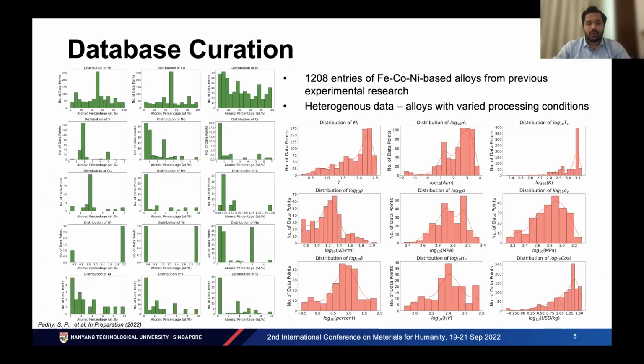Therefore, what I did was to build a database of 1208 data entries of iron, cobalt, nickel based alloys from previous experimental research. Now, we limited the addition of other elements to a maximum of 10%, and the distribution of the elements can be seen here in the left-hand side image.